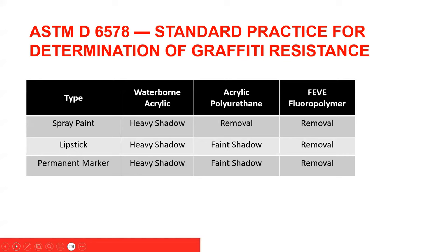So the spray paint was considered a heavy shadow for both, the acrylic was a heavy shadow for spray paint, lipstick, and permanent marker. The acrylic polyurethane, the spray paint was completely removed with faint shadows for the lipstick and marker. And the fluoropolymer was full removal of all three. So a very different outcome depending on the top coat that was selected.